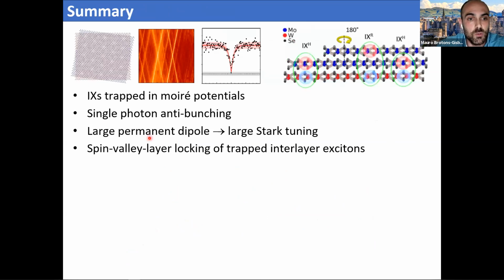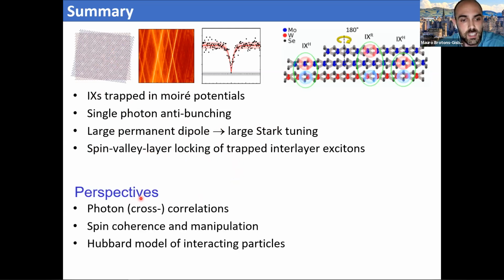And with this, I'd like to wrap up this second part and tell you that I hope I convinced you that we can trap interlayer excitons in the moire superlattice created by two rotated layers. That these excitons are indeed single photon emitters. That thanks to the large permanent dipole, we can use the Stark effect to tune the emission energy. And that we can create heterostructures where we have spin valley locking of these interlayer excitons. And with this, I guess again this opens some perspectives for future work.